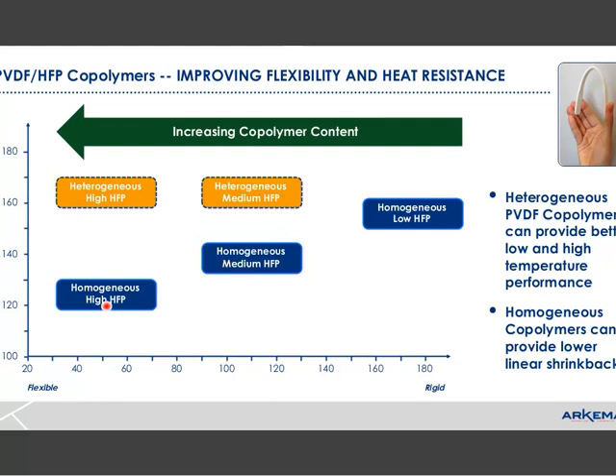This limits its use at higher temperature applications, but some of the benefits are that these products are very, very easy to process, and they tend to have very low shrink back. The newer materials are heterogeneous in nature. The benefits with these heterogeneous structures are that they provide a high melting point, so they're inherently rated for 150 degrees C, but they also have very good low temperature properties. And there's a wide range of flexibilities available.